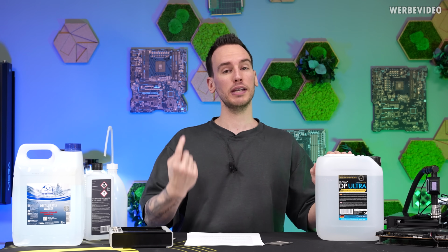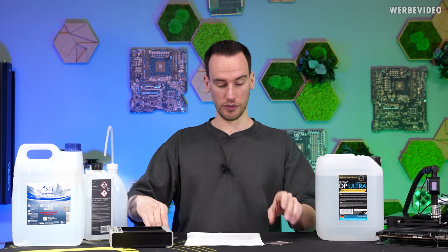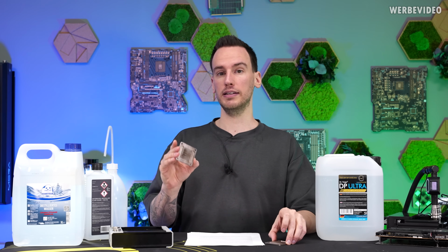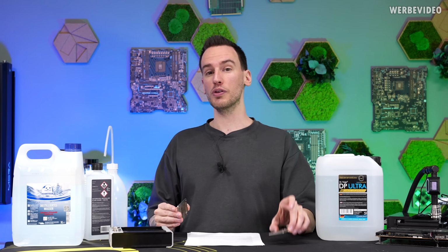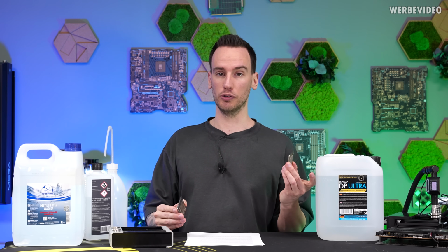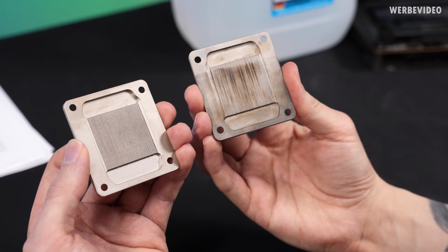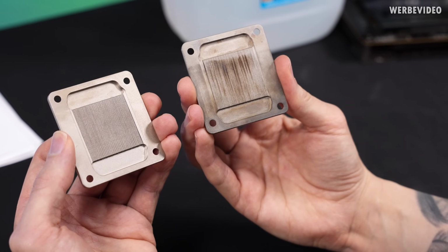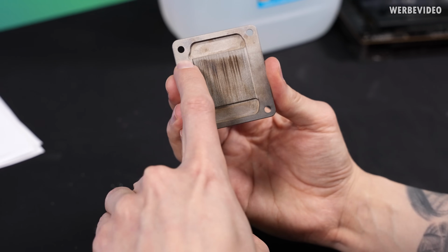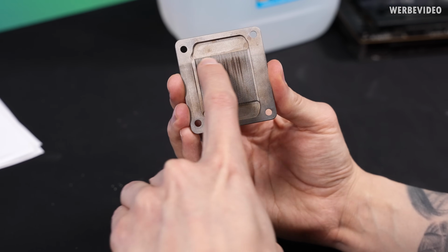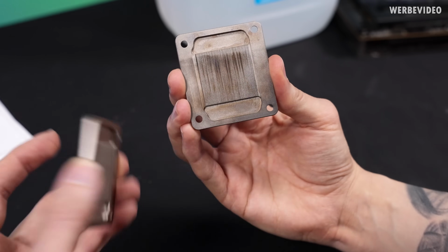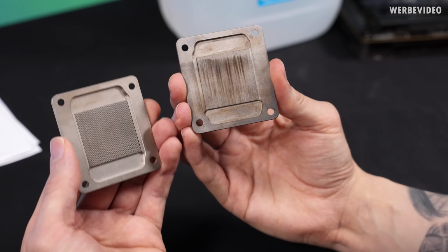We also ran the same test again, the same corrosion test with a similar part, same nickel plating, same nickel thickness, and also three times as long with the DP Ultra. Let's check the results. In my right hand, we have the sample that was submerged in the distilled water. You can also see the line until where the liquid was at. Underneath, it's really bad.